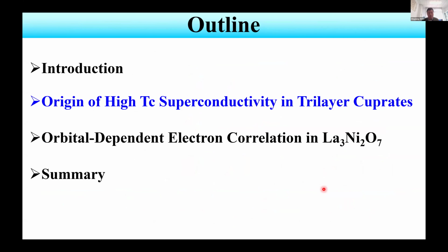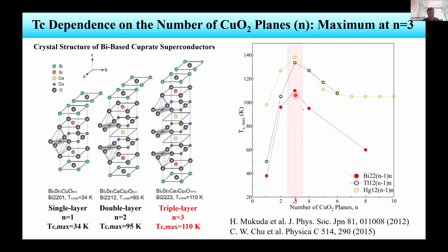So then I come to the first topic, which is about the origin of high TC superconductivity in tri-layer cuprates. As you all know, in cuprate superconductors, the TC depends sensitively on the number of CuO2 planes in the structure unit. Usually three layers has the maximum TC. As you can see from here, it holds for the bismuth system, thallium system, and the mercury system. Three is the best for the highest TC.